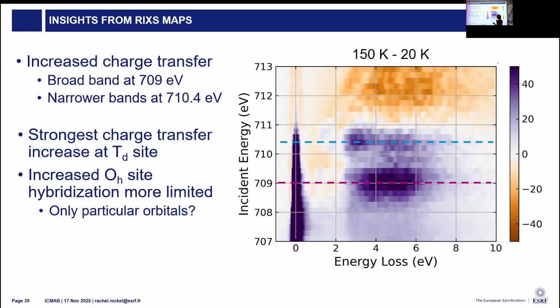So this is above the L3 edge, getting into the L2, and this ideally would be pure elastic compared to our quasi-elastic, where we have phonon and magnon contributions. And so the fact that that is going to 0 tells us that our normalization procedure and our processing is reasonable. But it also sets an idea of what the uncertainties are. So this has a very faint orange color, and this will allow us to identify whether or not we think these are real or whether it's an artifact of the processing.